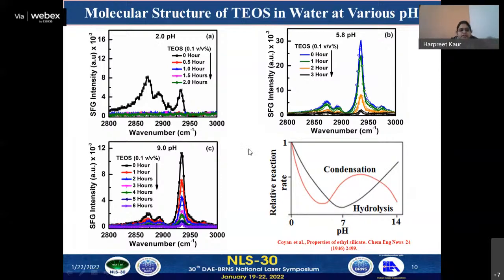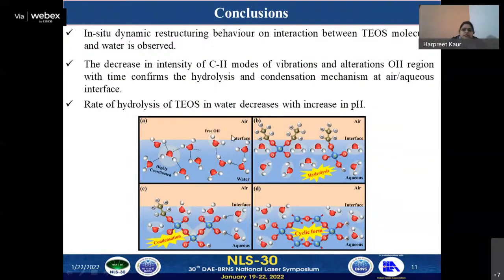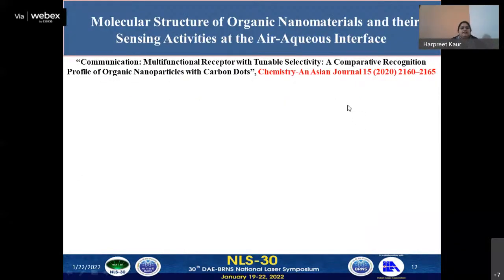So from these studies, we concluded that the changes we have observed in the CH and OH stretching regions of the SFG spectrum confirm the hydrolysis and condensation of the TEOS molecules at the air-aqueous interface, which further lead to form cyclic structures and nanoparticles. And also, we have determined the impact of pH values on the hydrolysis rate of the TEOS molecules at the air-aqueous interface. Next, I'll discuss the molecular structure of nanomaterials and their sensing activities at the air-aqueous interface.